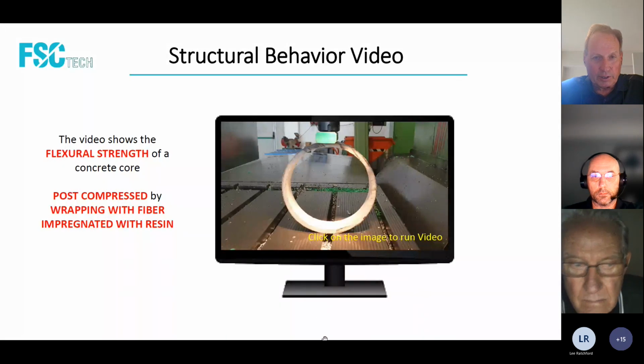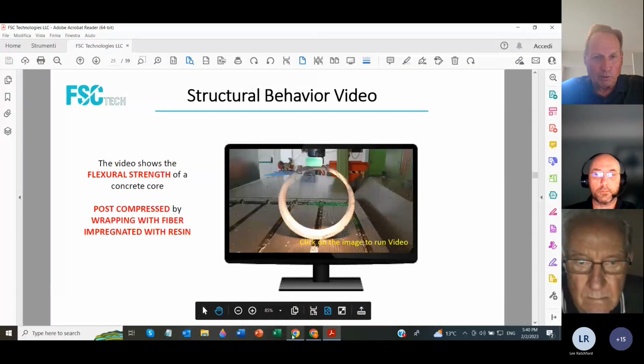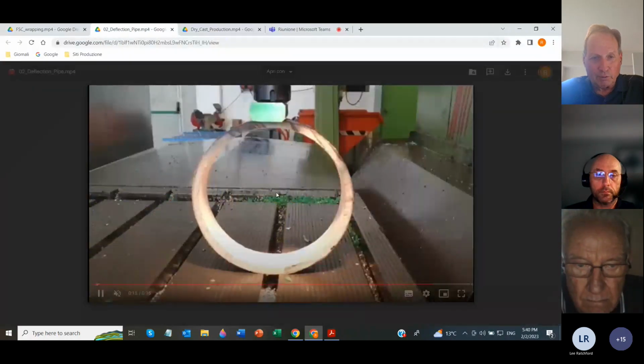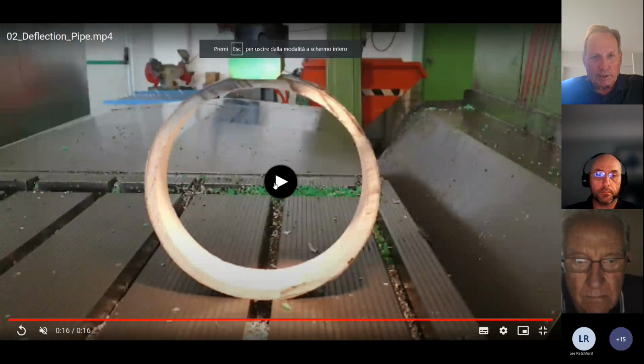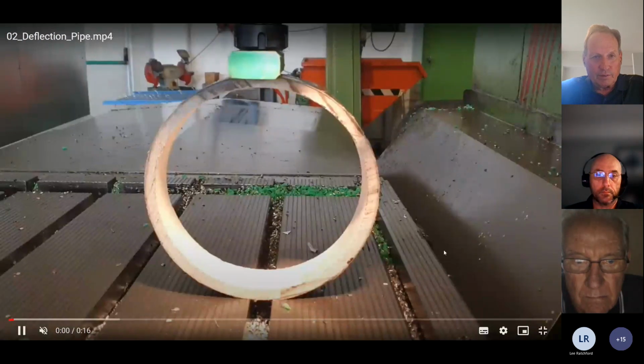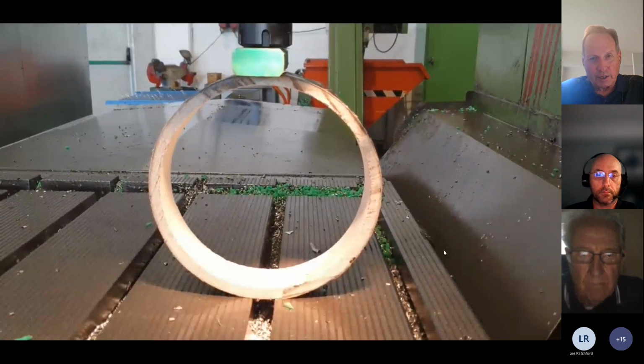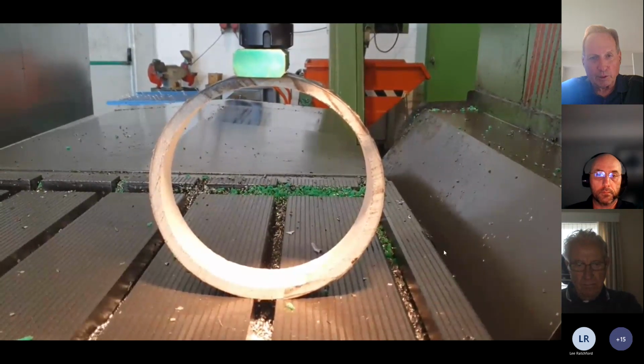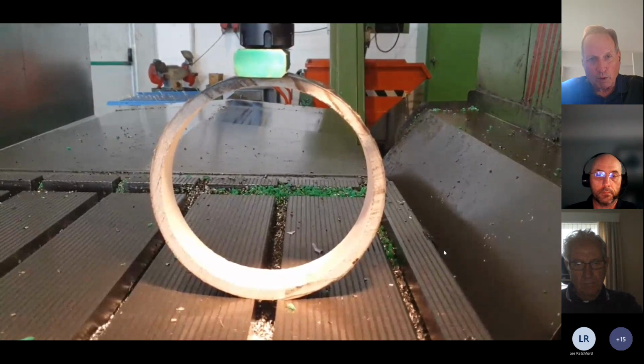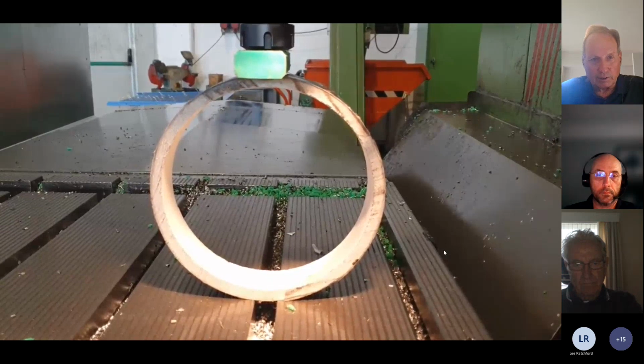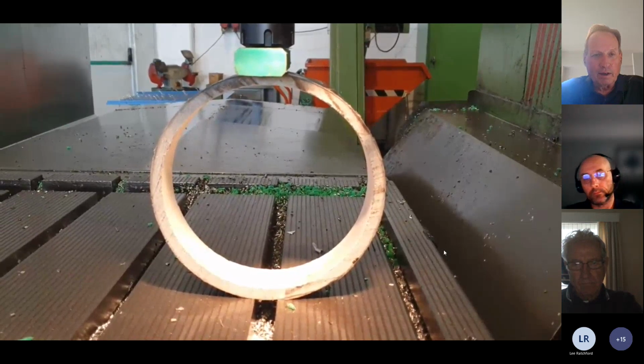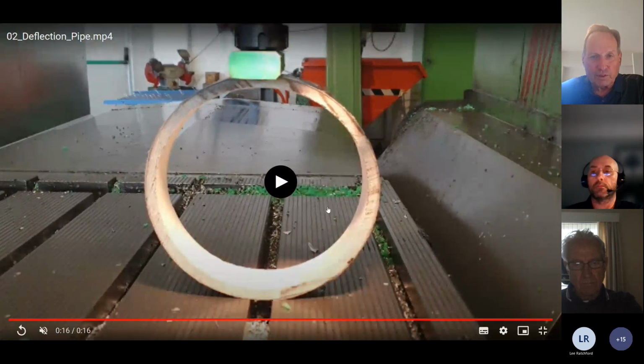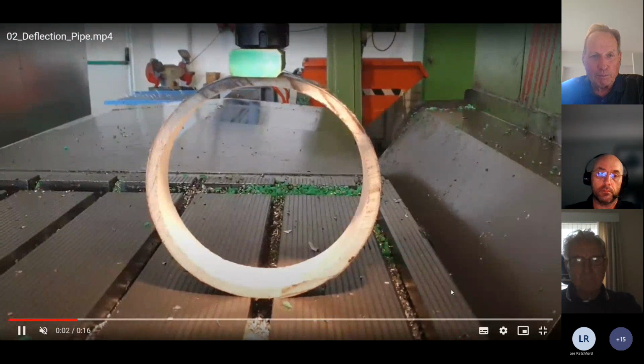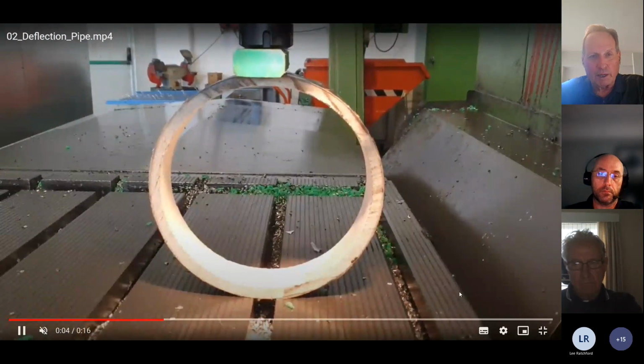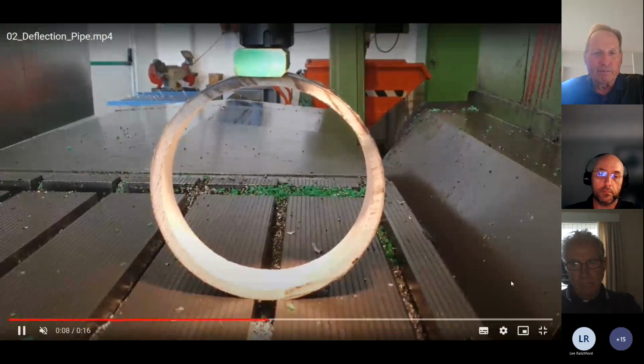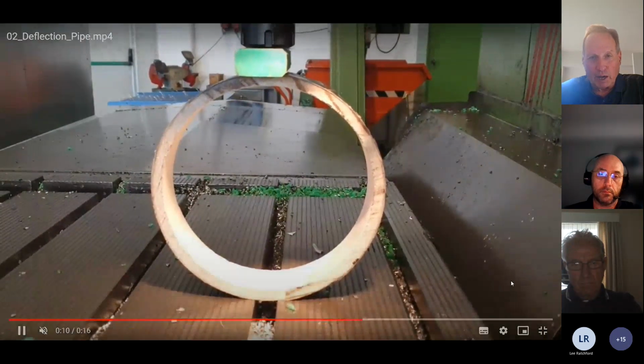So here's our little video. This is a pipe, and this whole research started with pipes. This is a 200 millimeter or 8-inch inside diameter concrete pipe with a 10 millimeter, or a little less than half-inch, wall that's been wound with the FSC technology and put into this post compression. And you can see it has a very high degree of flexural strength. When we showed this to the people at MXV, which is owned by the Association of American Railroads, the engineers ended up dubbing it flexible concrete.